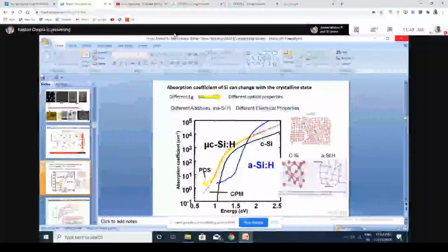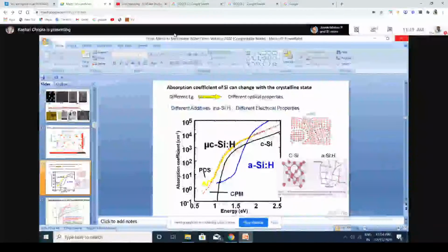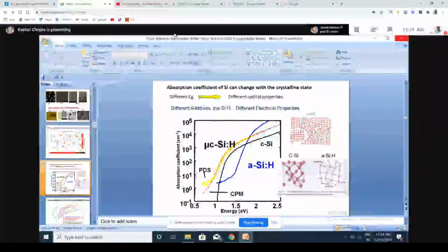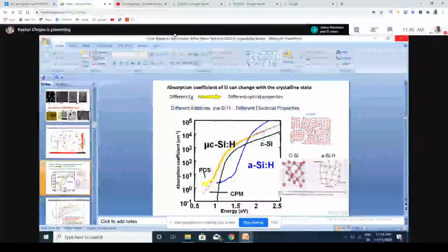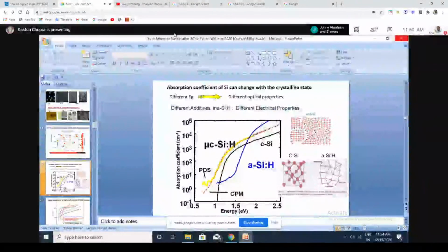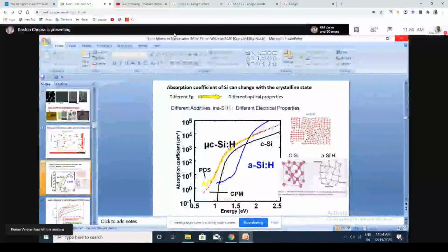give them mobility. So you cannot form crystalline silicon unless you give a lot of temperature, high temperature, good nice surface. They will not. Otherwise, they'll get stuck in the mud and they'll form amorphous structure, as you see in a mud. And when you form amorphous structure, naturally bonds are broken. And when the bonds are broken, then you can put any junk into it. So this was a great discovery.